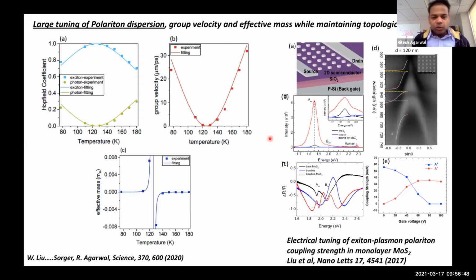In 10 or 20 degrees, how much does a photonic mode respond? Pretty much nothing. We've done experiments where it shows no measurable change. But if you have a topological polaritonic system, we can control the properties of these polaritons very significantly. And again, in the device context, we want to integrate this field effect transistor type geometry in our topological structures and electrically tune these properties. So that's a work in progress.